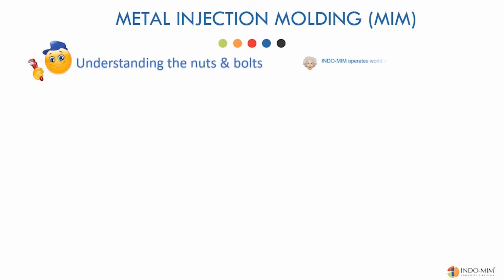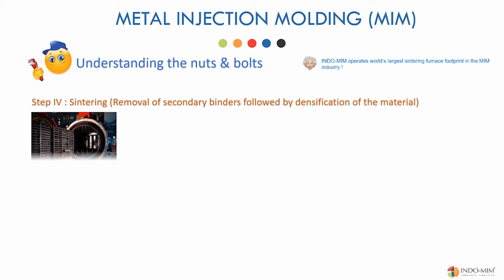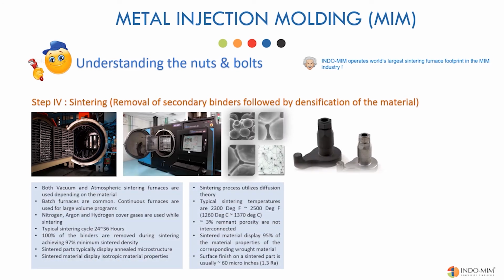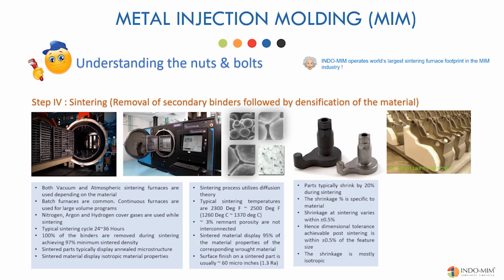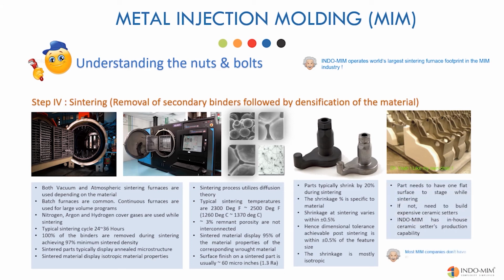Brown parts are now moved to sintering ovens. Sintering furnaces can be batch type or continuous type. Batch sintering furnaces are usually vacuum furnaces with nitrogen, argon, or hydrogen cover gas. Continuous furnaces use combination of nitrogen and hydrogen gases as the cover gas. Sintering temperatures depend on the material, usually range between 2,300 degrees Fahrenheit and 2,500 degrees Fahrenheit. Sintering cycles are between 24 and 36 hours long.